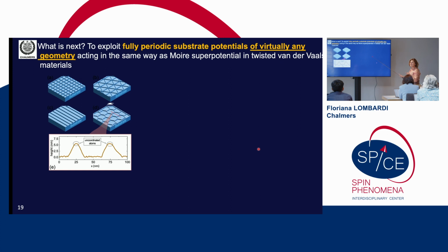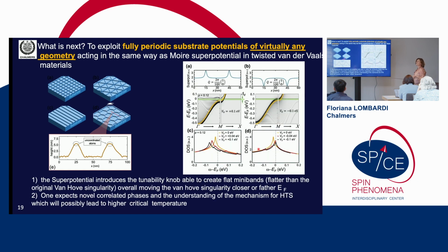And this is my last transparency. What is next? Well, this reconstruction happens naturally when you anneal the substrates, because we want to get untwinned films. But the next step is to pattern any possible geometry one wants, in the same way as Alex has shown for gallium arsenide, and to explore what these geometries, which can have symmetry and also distance between steps at will, will do from the point of view of the band structure.